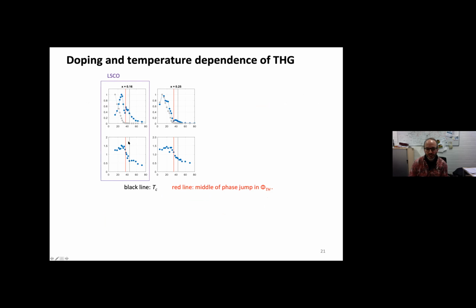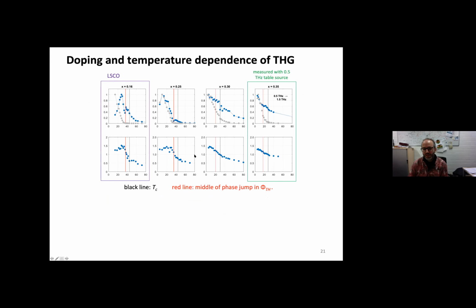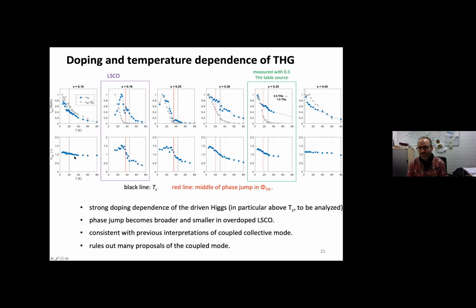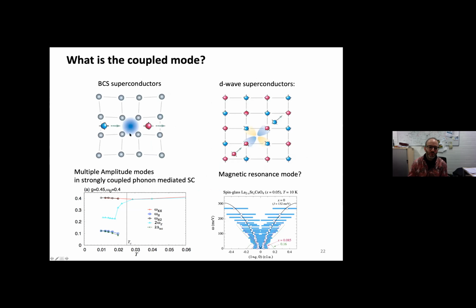And if you go to the overdoped regime, what we can see, maybe just look here at the phase jump of the system, is that this phase jump starts to smear out more and more if you go away from optimal doping towards the overdoped, and it goes fully away in the fully overdoped regime. And also in the underdoped regime, basically this phase jump fully disappears. And that is already ruling out some scenarios like the simple phonons, or at least it would be difficult to understand this with simple phonons. But these magnons, for example, are a big player that are still in this game, because the phonon modes should still have very, very strong resonances in the system, while these magnetic resonance modes usually are known to smear out and disperse as soon as you go away from optimal doping.